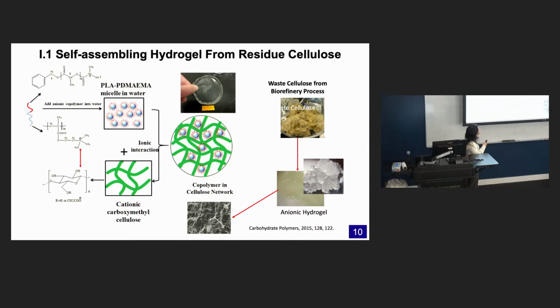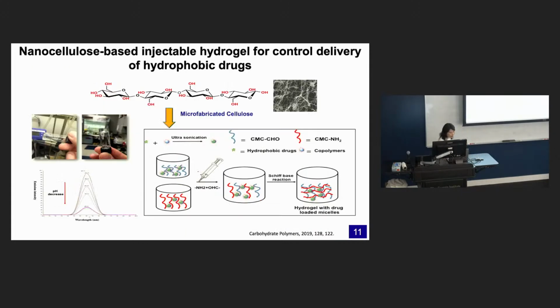So we can make a transparent film, but the film properties depend on how we tune this copolymer structure. We can tune their strength, and their elastic and plastic properties, based on the molecular structure of these materials. Further on, based on this hydrogel, we used nanocellulose to make an injectable hydrogel. We first got the CMC, and then we functionalized this cellulose with CHO and NH2 groups, grafting these groups at the end.